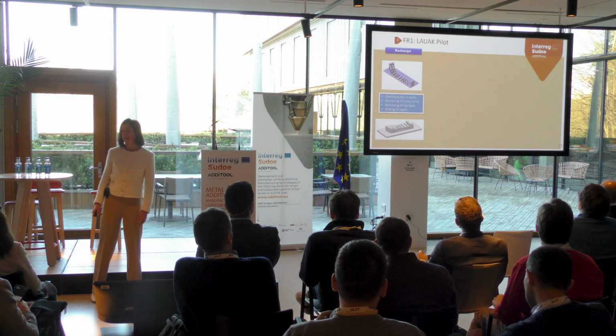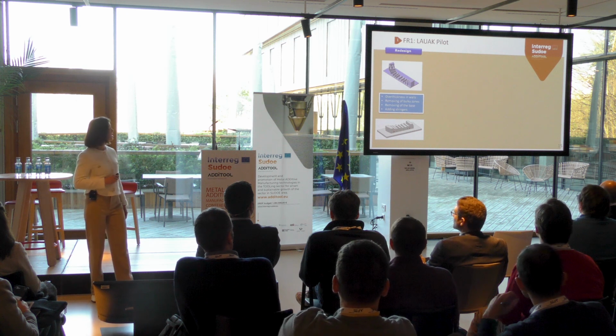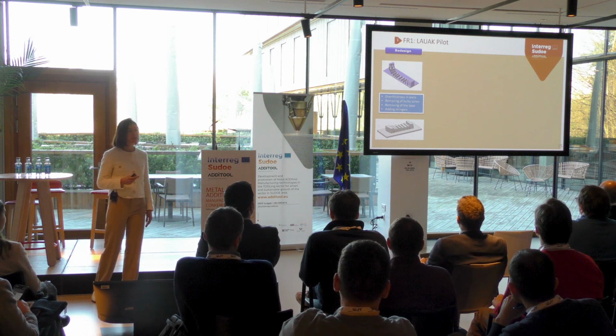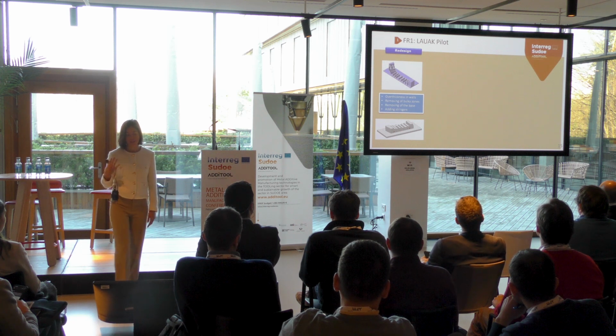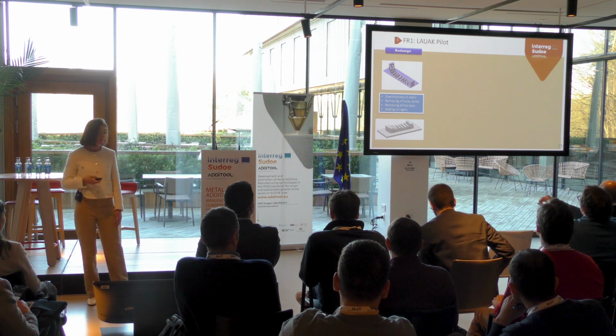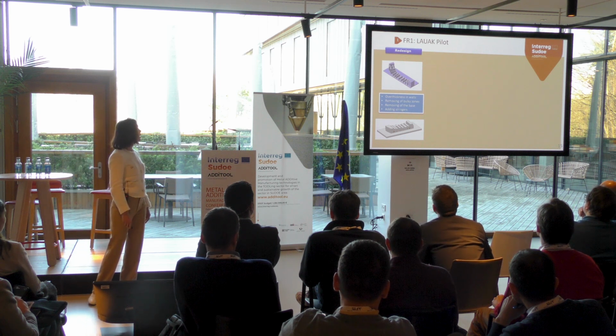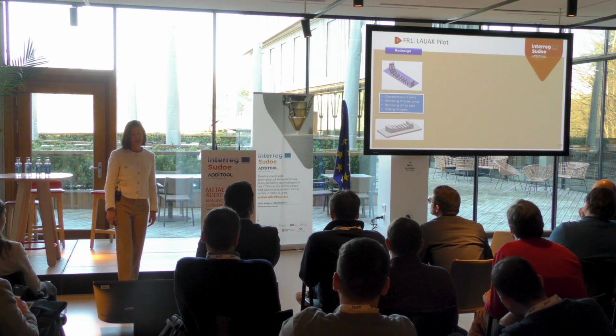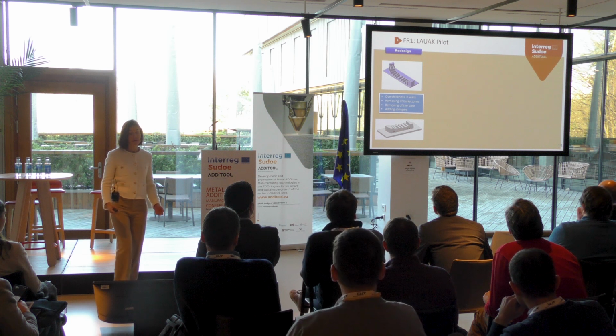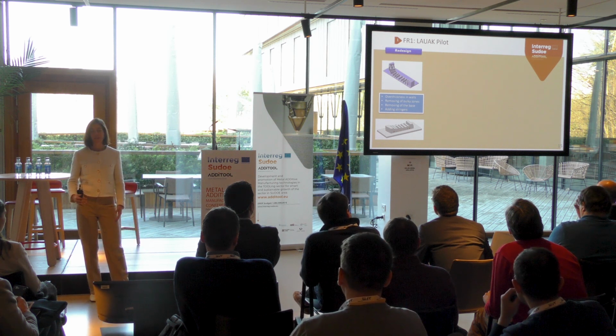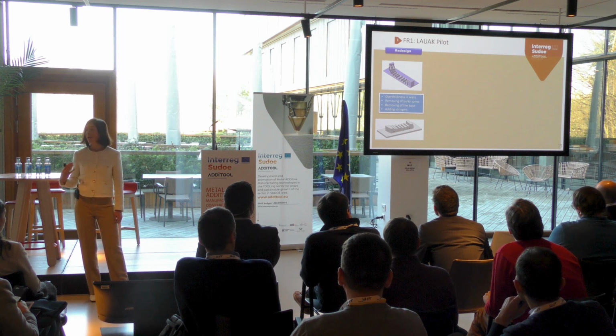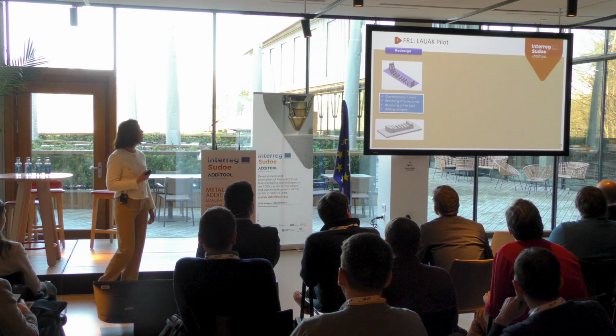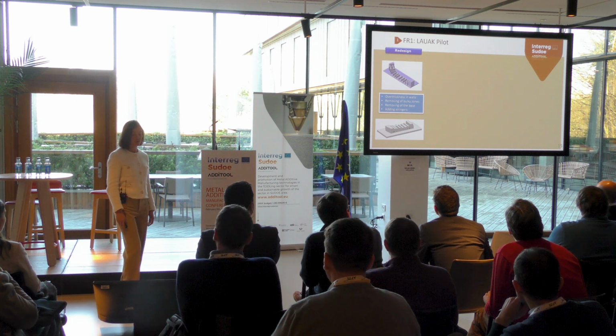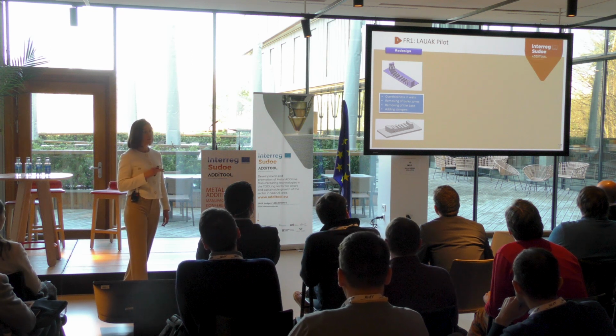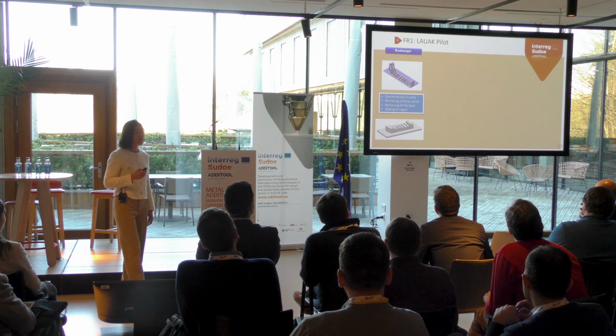Regarding the part, for each technology and in each part, we applied an over-thickness, taking into account the last step of machining. Concretely in the wire arc technology, the part was also redesigned to apply as little material as possible in order to reduce possible distortions. So we removed the bulky zones, removed the base, and added some slim stringers to avoid distortion during manufacturing.